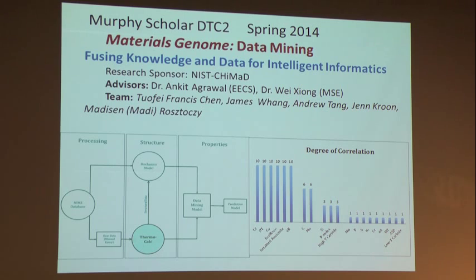And so one of the demonstration projects we actually ran in an undergraduate class last year was to use a fatigue property database from NIMS in Japan, which had about 400 different alloys, their composition and processing, and their final performance, to translate that information with the CALPHAD thermodynamics into structural attributes, and then mine that. And we were able to show, compared to the brute force approach, we could get a more accurate representation of the process structure property relations.